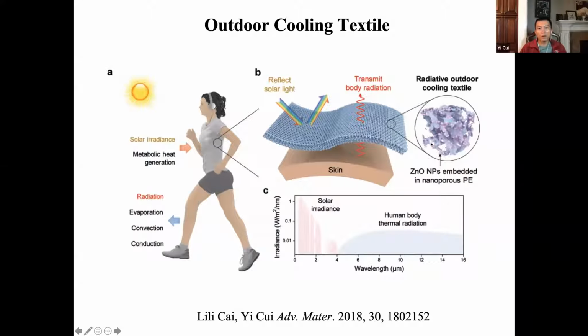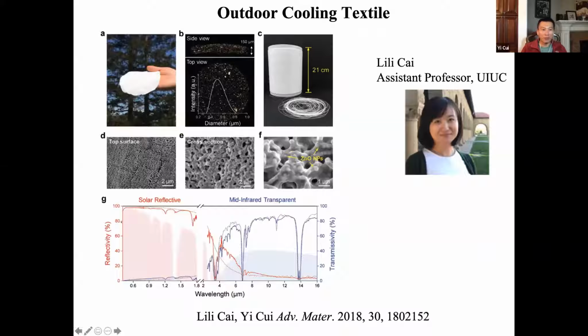We put into this zinc oxide particle. You pick the right size, about a micron also. You can scatter the visible light near infrared, but not the mid infrared. The mid infrared still going out. Yeah, and with this design, we did a measurement, careful measurement of spectrum, and also mimicking the human body, using the artificial sun. This is a really big, compared to under the sun, the delta T, the type of cooling you can have is gigantic.